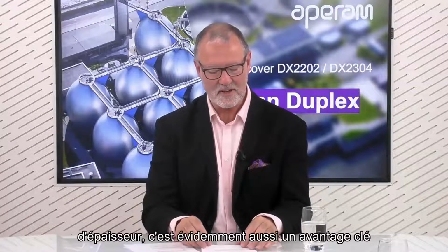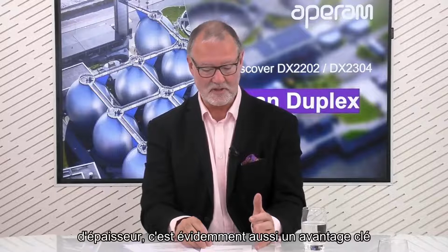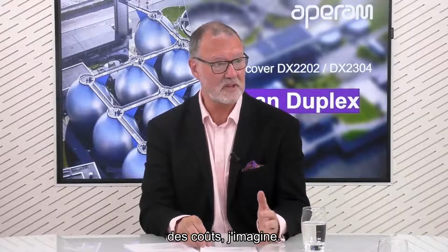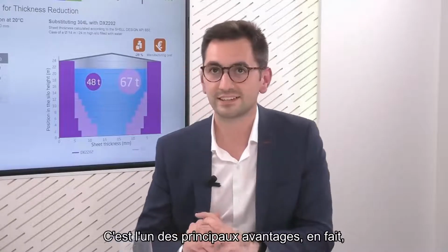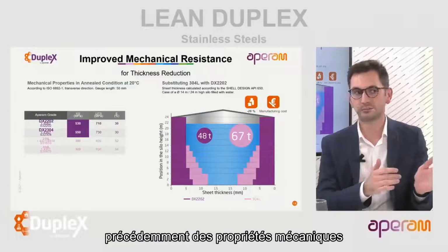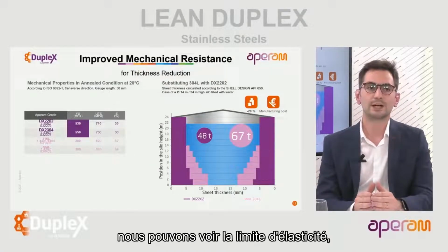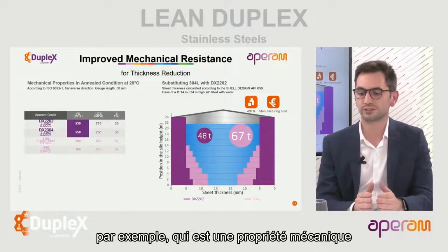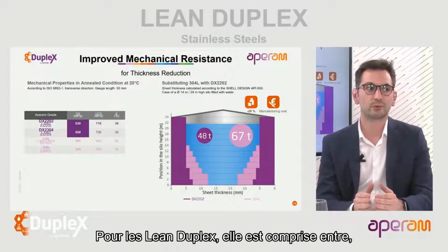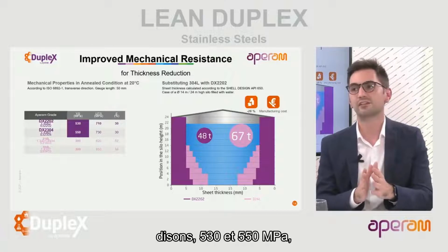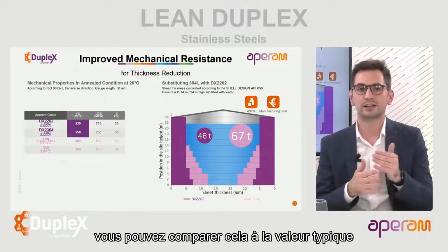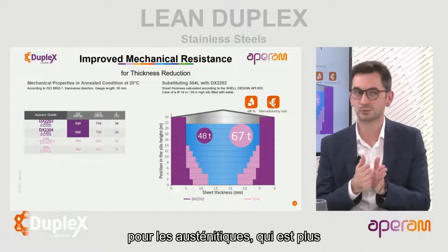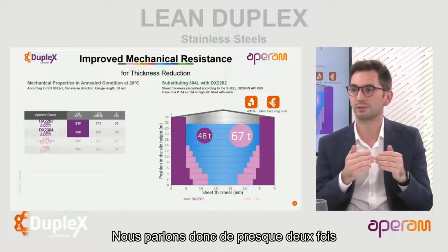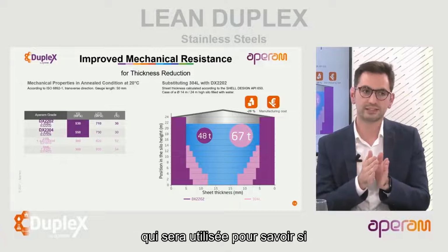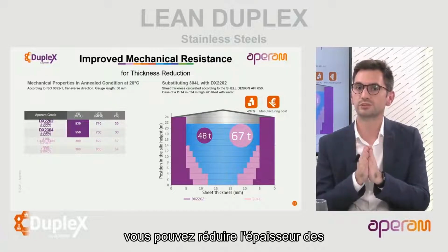Now, in terms of thickness reduction, it's obviously also a key advantage because it can bring additional cost reduction, I imagine. Can you tell us about that? Of course, that's one of the main advantages actually of Lean Duplex as well. I was talking before about the mechanical properties of Lean Duplexes. We can see the yield strength, for example, which is a very important mechanical property of the material. For the Lean Duplexes, it will be between, let's say, 530 and 550 megapascal. You can compare that to the typical value for austenitics, which is more or less 300 megapascal. So we're talking about almost twice the yield strength, and that's the value that will be used in order to know if you can reduce the thickness of the sheets or not.